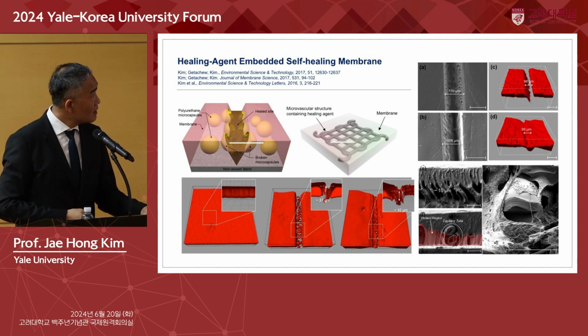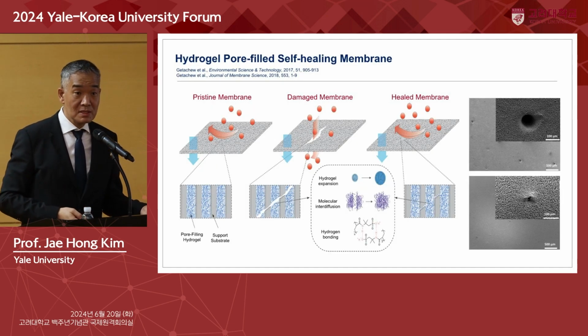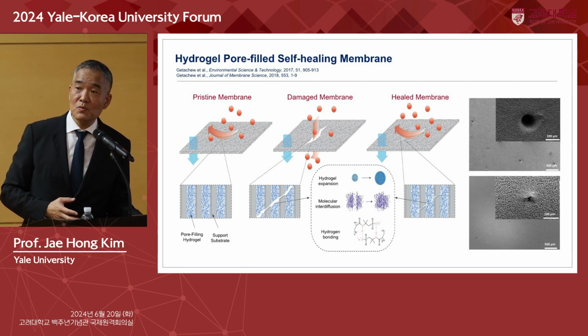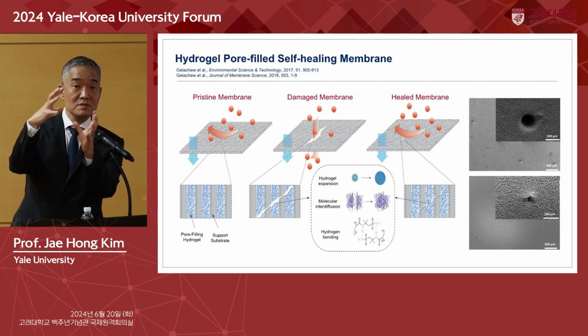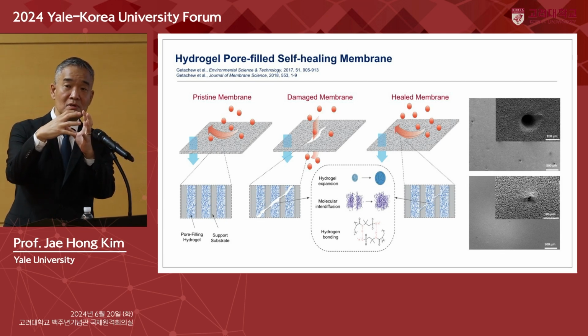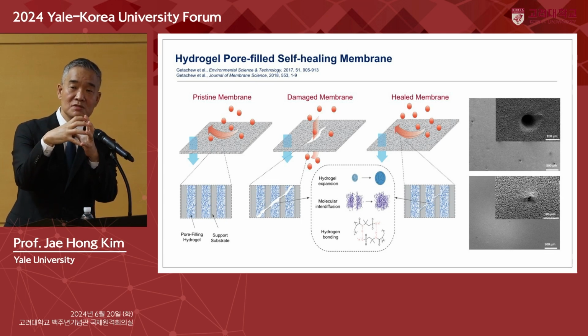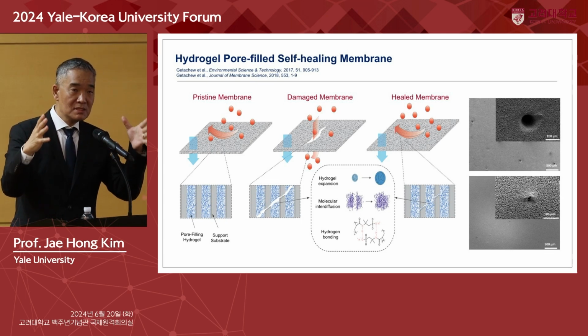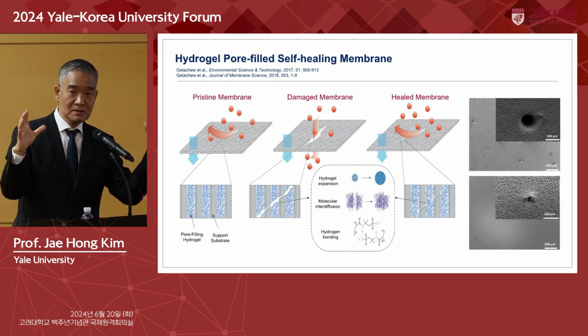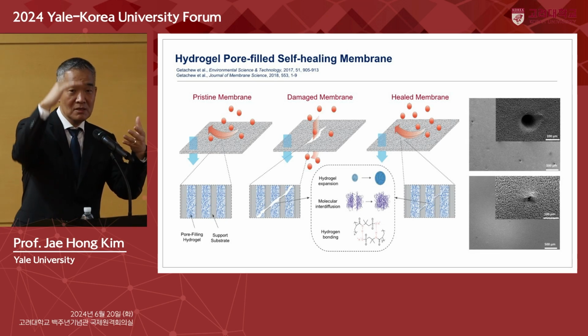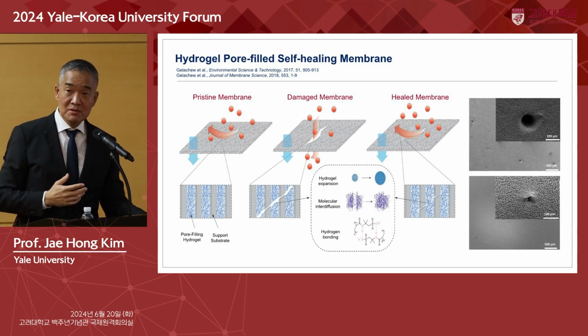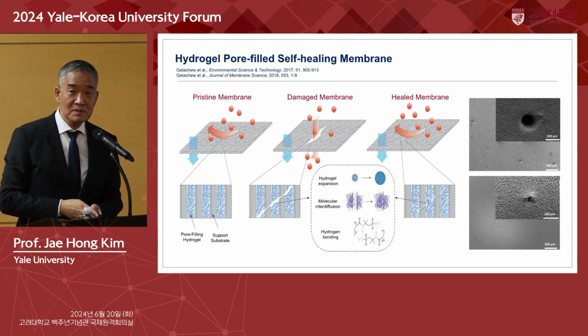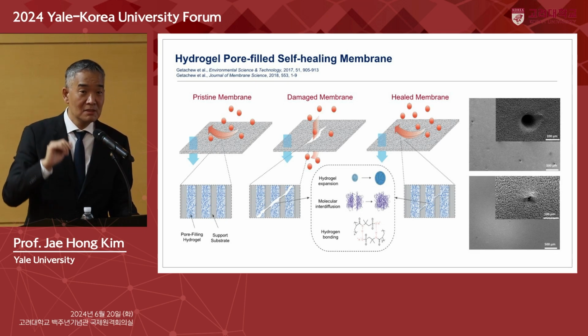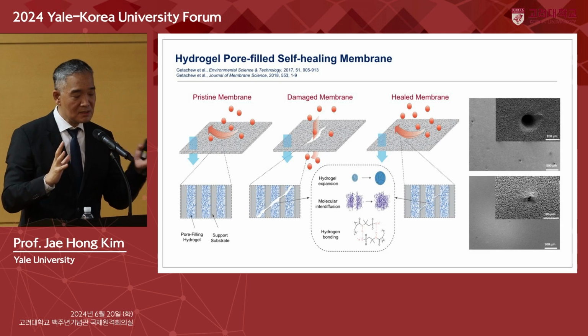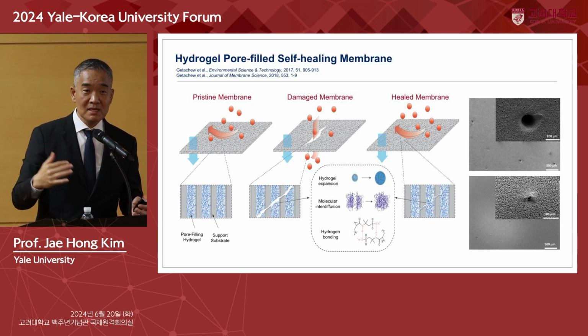So our third generation is actually using hydrogels. We learned that there is a way to confine the hydrogel. You have a certain porous structure, and then you bind the hydrogel inside the pore, just the right amount so that it has a tendency to expand. The substrate is basically a skeleton, and the hydrogel, like what you use for diapers, is the membrane, okay? We control the thickness, and water passes through the hydrogel. The good thing about hydrogel is that if it gets damaged, it heals back. So now you have a membrane that you poke, and it heals, again and again and again.